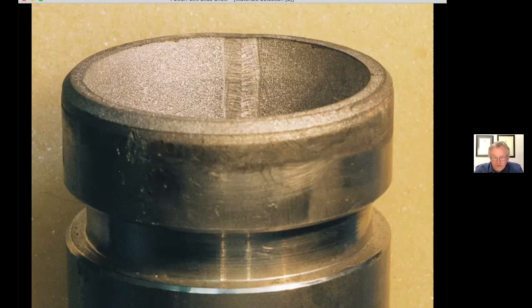The operators then attempted to address the issue by lining this very expensive material with another very expensive material in the form of Teflon. And the problem was that the Teflon lining was not fully continuous, and they got even faster failure. And when we investigated this situation, we found that there was a variable speed drive pump in the system which had not been properly earthed. And there was an AC current interference component that was going to earth through the piping.